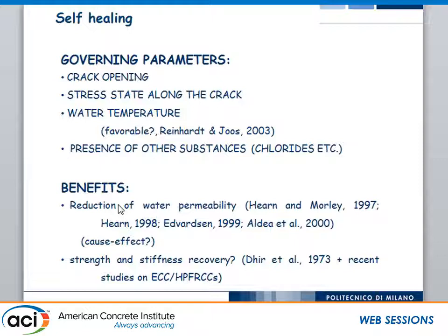We have that the crack is always in a water-saturated condition because what you measure is the flow of water through the crack. We would also like to know if the material is able, and to what extent, to self-heal when exposed to any other kind of environmental condition, which can be a moisture atmosphere, a marine environment, or any other kind of environmental agents. And when using HPFRCC, when we explicitly take into account the ability of the crack to transfer the stress, we would like to know how effective is this stress transfer and its magnitude a long time after, due to degradation and in case of self-healing.